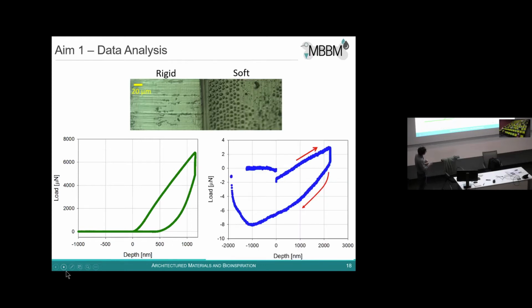The problem is that when you indent in a soft material, you have very different behavior. When you are approaching the surface of the material, you have a jump into contact that you see because the tip is approaching the surface, and then you are indenting, and then you have large adhesion forces that you see by this negative peak here. And so this changes the procedure and the way you have to fit the data.